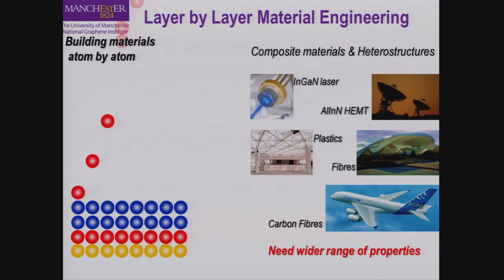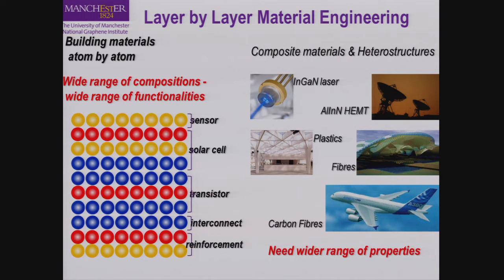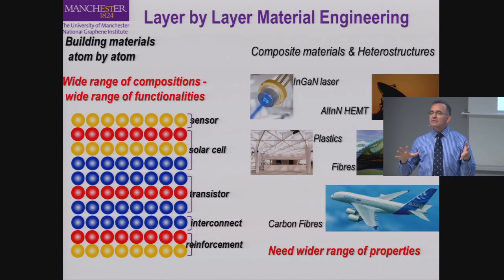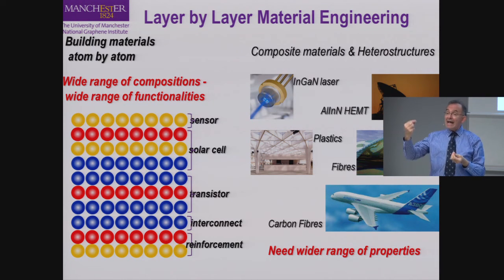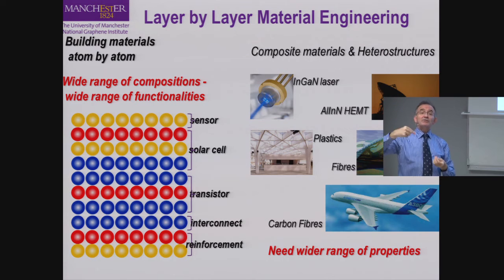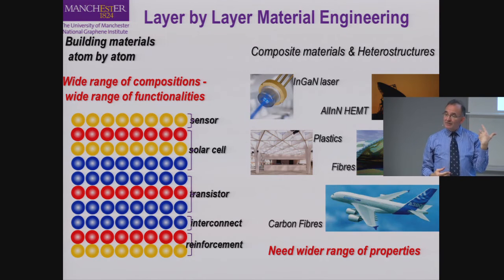And of course, the advantage with graphene is the opportunity to build multifunctional composites, where certain layers in our multi-layered composite construction can be responsible for providing the strength, the stiffness, the optimized toughness, the heat storage or dissipation, or they can act as sensors to detect damage in the composite structure when the composite structure goes into service. So they can sense impact events. So when the aircraft mechanic walks along the aircraft composite wing and drops the spanner, the graphene can act as a sensor to report the impact event that took place.